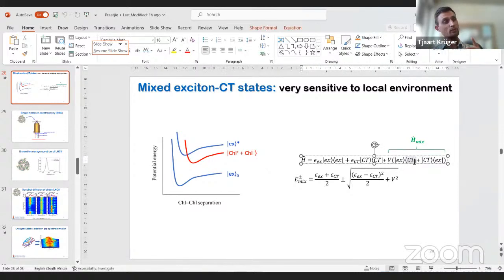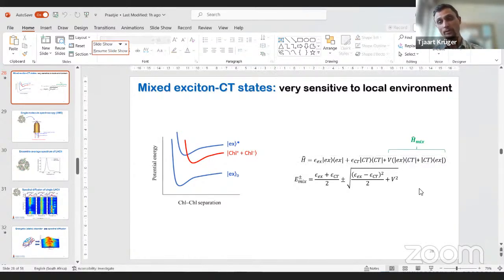Okay, so because of the presence of the charge transfer state, which has a strong permanent dipole moment, that leads to a very strong Stokes shift because of the large reorganization energy. So one has large oscillator strength and a large redshift. And this is exactly what we also see in the experiments. Nice. Very good. Thank you so much for explaining.